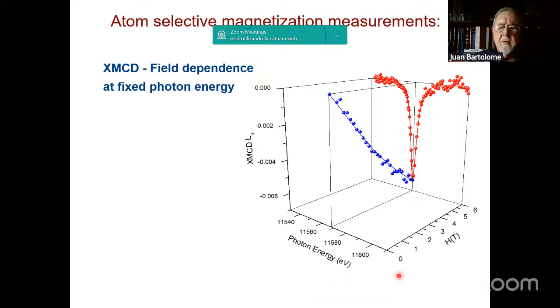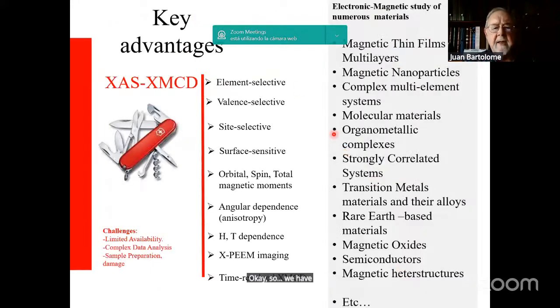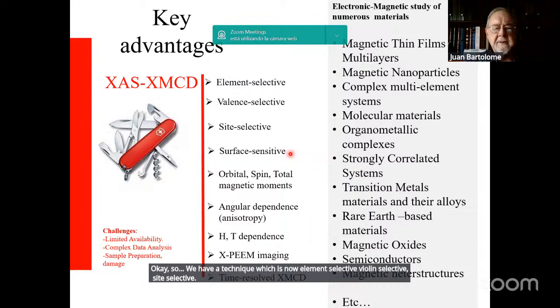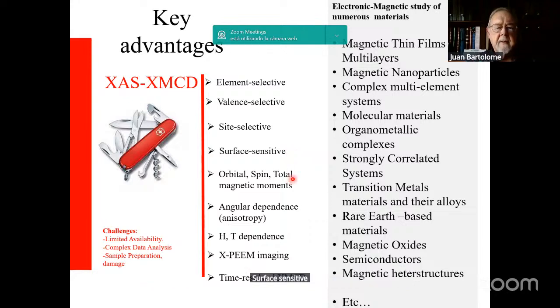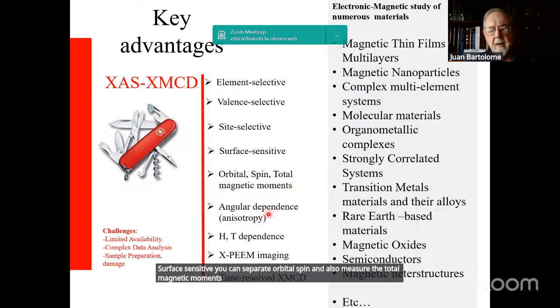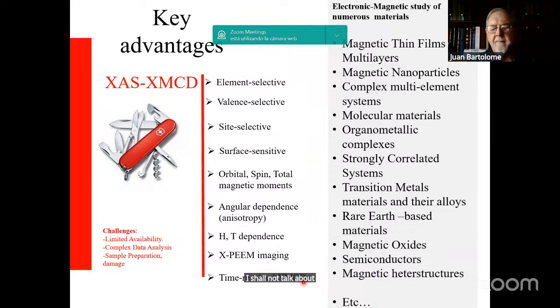Okay, so we have a technique which is now element selective, valence selective, site selective, surface sensitive. You can separate orbital, spin, and also measure the total magnetic moments, angular dependence. You can measure as a function of applied field and vary temperature. And I shall also speak about imaging with XMCD, which is called the technique X-PEEM. I shall not talk about time-resolved XMCD, since I have not direct experience in that.